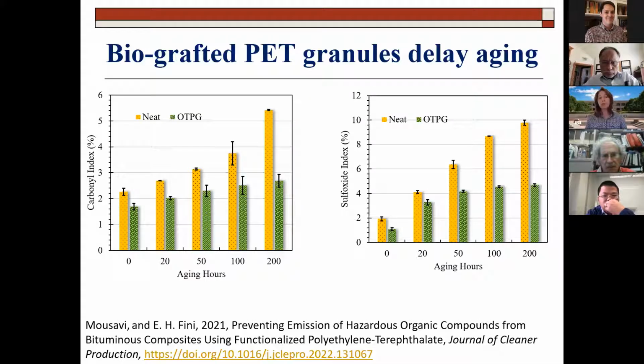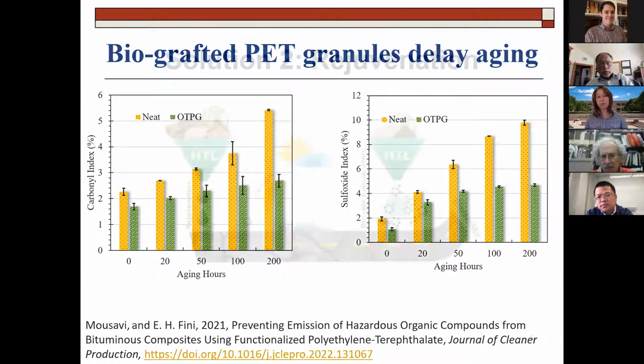What we have done with this bio-grafted PET is the green one. We just distributed those inside our asphalt and measured the same indicators. You can see the green is significantly lower than the yellow bars all the way. So maybe that would be a way to reduce aging. And a caveat on the side is, we always talk about plastic being non-biodegradable. It doesn't go away. It lasts 100 years and so forth. Well, if it is that durable, maybe we can take advantage of it right here. If it doesn't go away, maybe I can use it as a sacrificial agent or a molecule that can prevent aging.